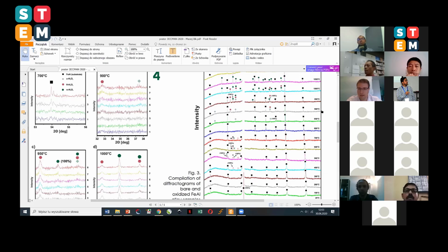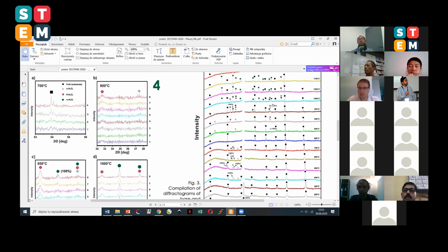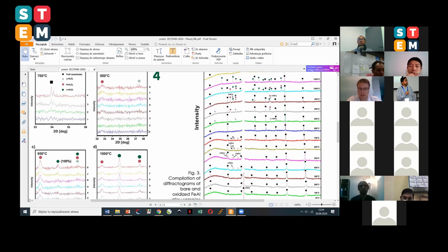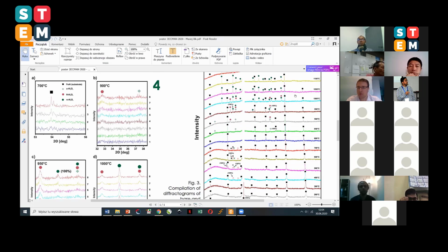Because then further at the higher temperature region, we saw some differences in comparison to the first study, to this first part, because even though we saw gamma alumina at a temperature of 850, we saw a shift in the temperature ranges for the further phase transitions. So first of all, gamma to theta was observed 50 centigrades lower, so at 900. And then at 950, we observed once again the first formation of alpha alumina. However, the full transformation from theta to alpha alumina was observed 100 Celsius degrees below, so at 1000 Celsius degrees.